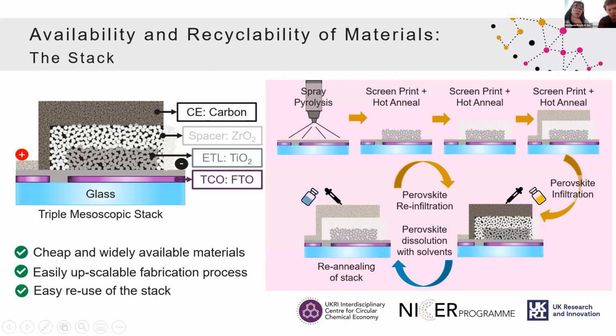And if we were to remanufacture them, the only thing we need to do is dissolve the degraded layer with some solvents, re-anneal the stack to dry it off and remove all sorts of impurities, and it'll be a matter of just re-injecting again. So as you can see in this project, we're considering circularity by design so that we are always able to do this cycle. Eventually, I'm assuming at some point they could break, but they are quite common materials. They could be scraped off the conductive glass surface, crushed and separated, and we could start again.